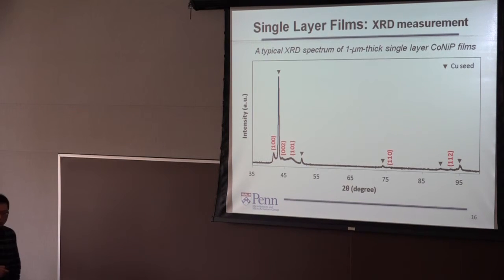So we also want to check using XRD whether we have a well-defined in-plane anisotropy, I mean the in-plane texture. So as we see, a relatively large HCP 100 peak compared to the 002. I didn't show the data from the powder form, but as you will see, this in-plane peak is much higher than the out-of-plane, indicating the c-axis of this HCP structure is aligned in the in-plane direction.